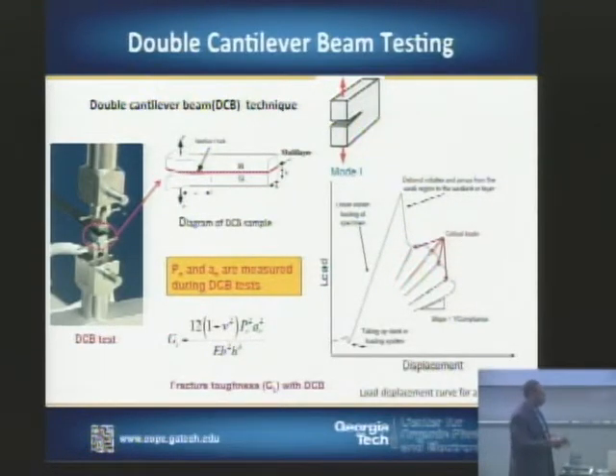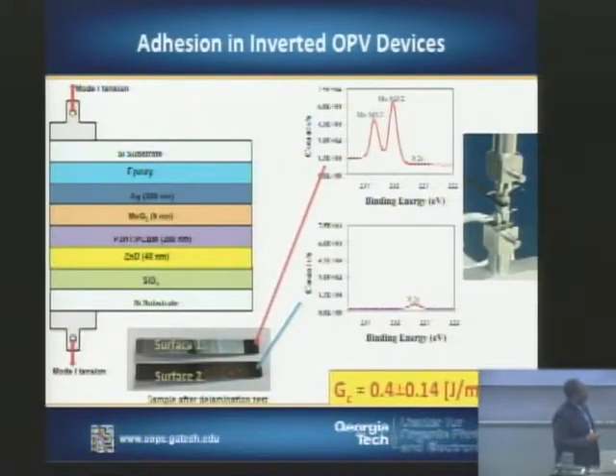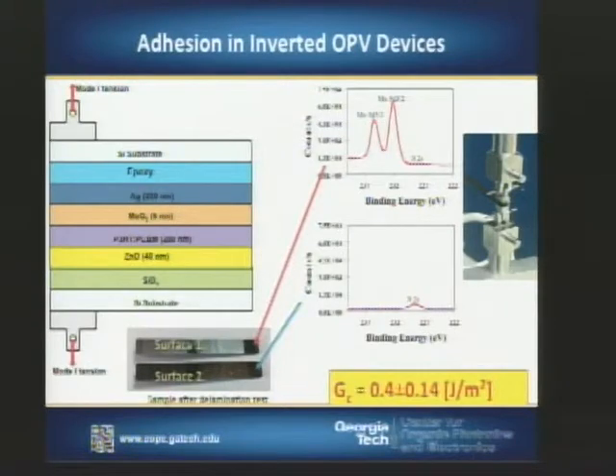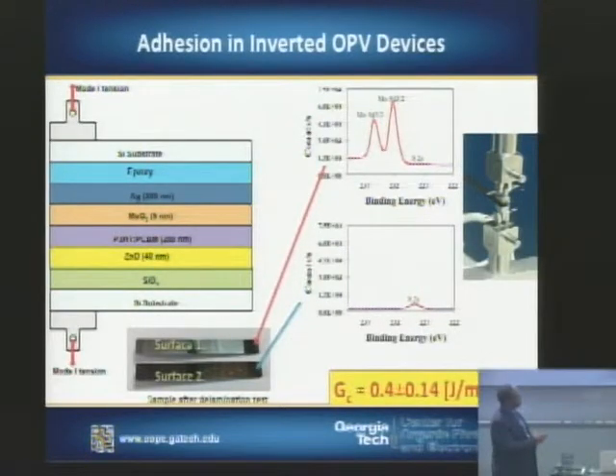The general gist here, of course, is that the higher that energy, the better it is for mechanical reliability. We've applied this to inverted organic photovoltaic devices, and this one is based on P3HT:PCBM. We've done some other materials as well. This is an inverted cell that has a zinc oxide and a moly oxide interface. When we apply mode 1 tension, we pull this apart. We can do XPS analysis of the surfaces after they've separated, and we can see that it is separating near the moly oxide and P3HT:PCBM interface. That is the weak link in this particular material system.